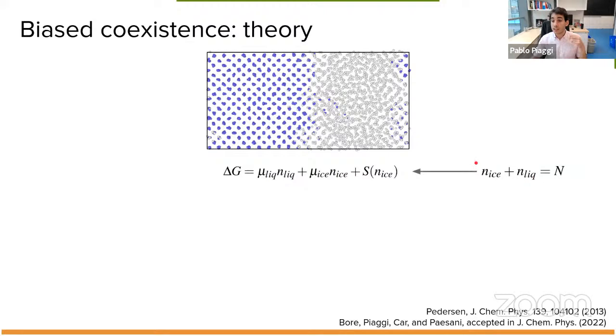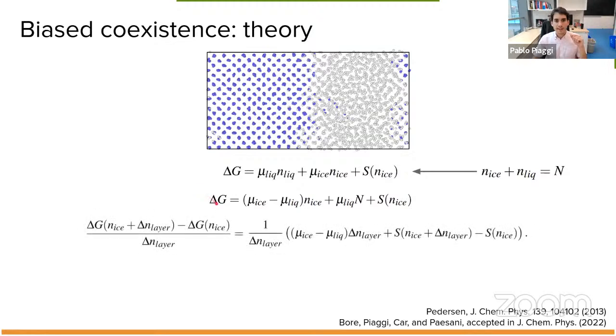Now, if we use what they call the equimolar dividing surface, that is the fact that we assign that all the molecules in the system N can be decomposed into ice-like and liquid-like. So we ascribe nothing to the surface. So if we do this approximation, well, it's not an approximation, it's a choice. We end up with this expression for the free energy. And what we can do is we can evaluate the slope over a full layer of the solid that we will try to form, and we arrive to this expression.